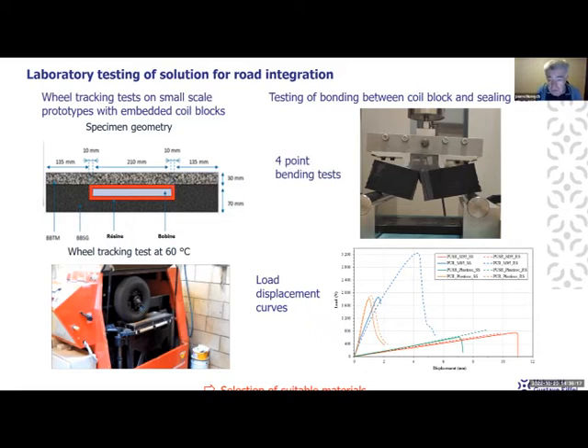And we tested the bonding between the coil block and the sealing resin, which is also very important because the system will behave well only if it is bonded. We did these 4-point bending tests on specimens with 2 materials, in black the coil block material and in gray the resin. So we tested the bonding resistance between the resin and the coil block. And we were again able to compare different resins and to select the best possible resin.